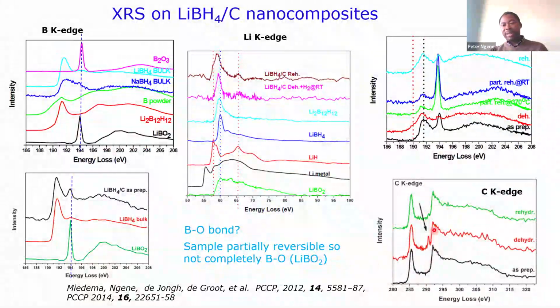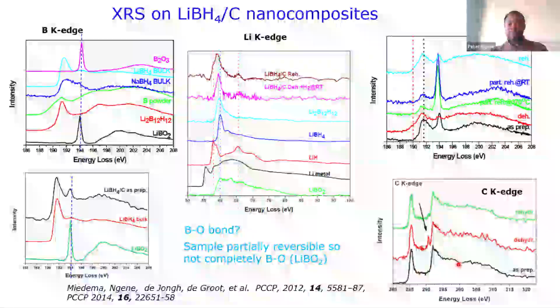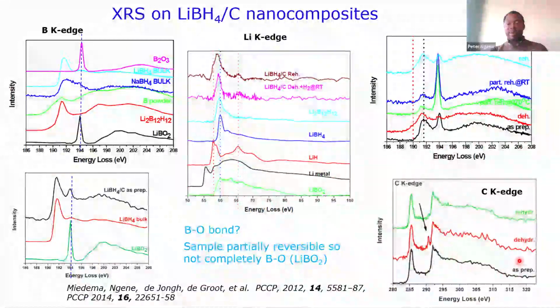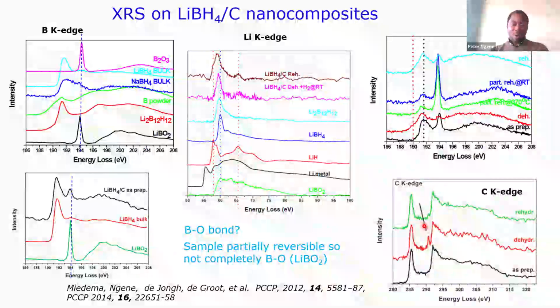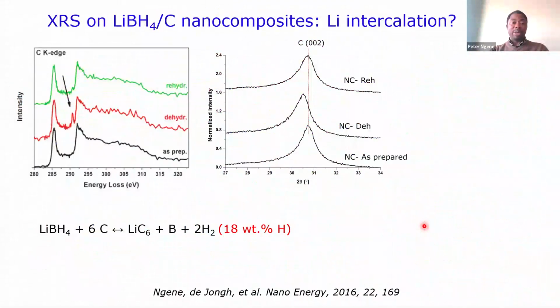But one interesting thing that we saw from this experiment is that if we look at the carbon edge, so this is the carbon edge of our material as prepared. When we heat it up and we remove all the hydrogen, so dehydrogenation, we do see some change here. And when we do rehydrogenation, so we put back hydrogen, so we form back lithium borohydride, these things seem to disappear. And we didn't know why. It took us a long time to figure out what was happening.